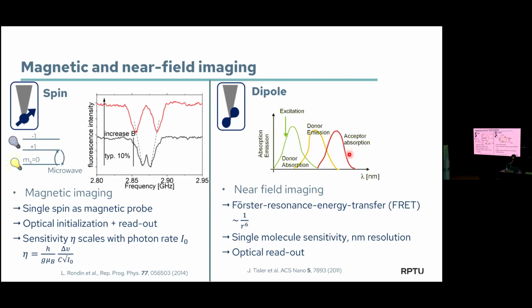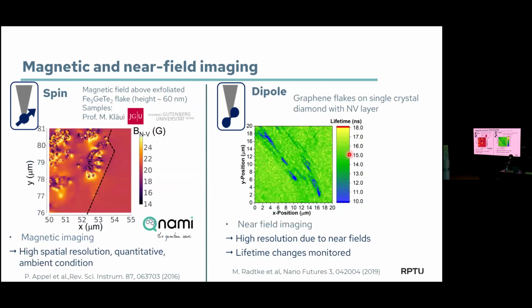And before I go into details, I would like to show you two first applications that show you what we can do with this technology. And the one here on this side is a magnetic image. It's a quite new one from a cooperation I have with the Johannes Gutenberg University in Mainz with a group of Matthias Kläui. And it's also one that we have for the first time recorded with one of our commercial NV scanning microscopes. What you see here is a material. In short, you can call it FGT. What's so special about this material? You can make ultra thin magnetic flakes by exfoliation. So it's something like graphene, just magnetic.